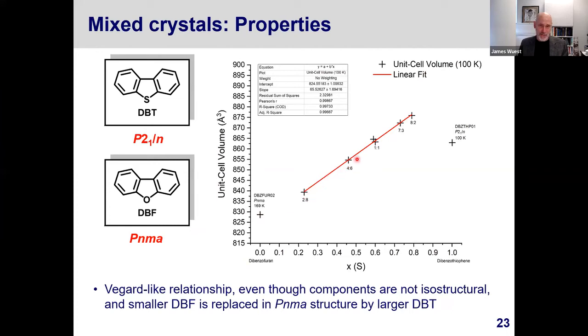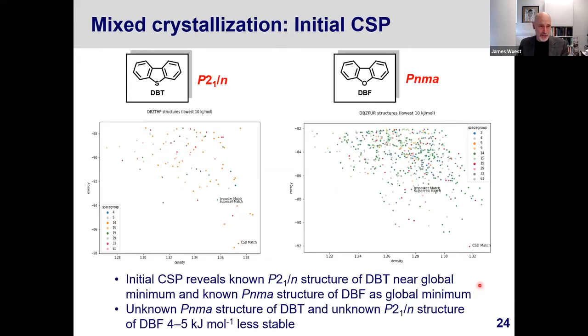Here are the plots of the unit cell volumes of single mixed crystals, and here is the known P2 structure of the corresponding thiophene. So it lies off the plot. It's a different structure. In fact, it's a more stable structure than the other one because it's more dense. The interesting observations. So again, we teamed up with Graham Day and his group to probe this using the methods of crystal structure prediction, and the results are preliminary.